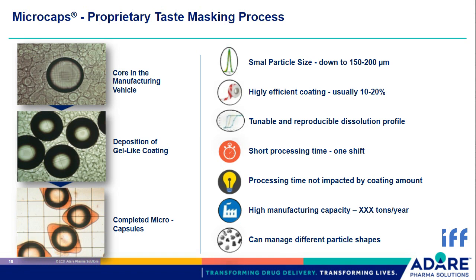During the process, we can induce the coacervation phenomenon, basically a sol-gel transition. And what you see in the background are the gel globules having a high concentration of the coating polymer, representing the second not mixable phase. The third phase is not visible and is represented by the residual solution of the coating polymer.